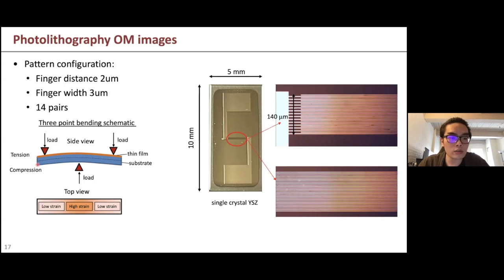So actually the strain is not uniform across the sample, and we grow the film on the top of the substrate so it can be subjected to the highest tensile strain, because the strain is proportional to the distance from the neutral axis.